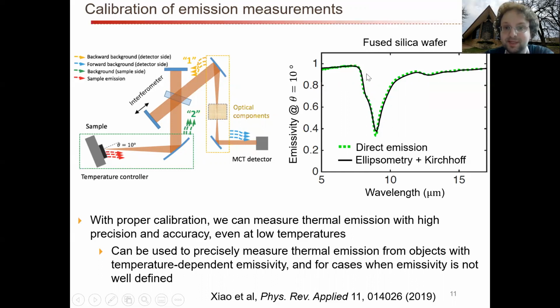And you can see that the emissivity that we extracted by appropriately calibrating our instrument is really, really dead on to what you get when you do ellipsometry analysis, apply Kirchhoff's law, and you're very, very careful about how you do this. So the method that we developed can be used to precisely measure thermal emission from objects with temperature-dependent emissivities for cases when the emissivity is not defined and so forth.